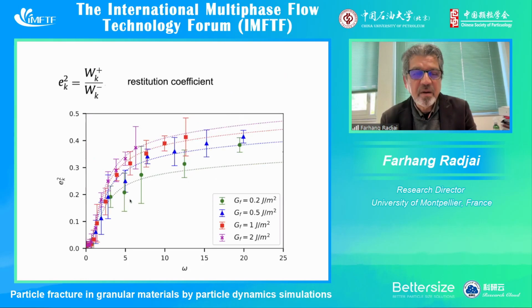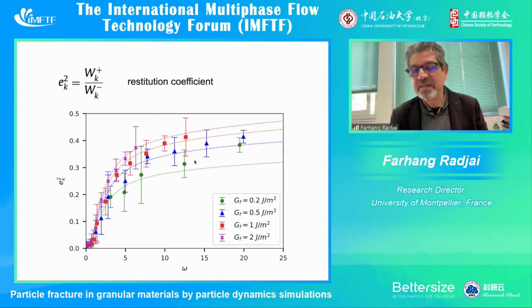Because I don't have much time, let's look at the restitution coefficient. We found that the restitution coefficient increases with this parameter omega all the time. In contact dynamics simulations, it is always increasing. So why increasing? Because as you see, for low values of omega, so typically small initial impact velocities, all the energy is dissipated either for fracture or by inelastic collisions of the fragments. But as omega increases, the restitution coefficient is increasing because the kinetic energy is transported away by the fragments. So part of the excess energy, which is not used for fracture, is carried away by the fragments.